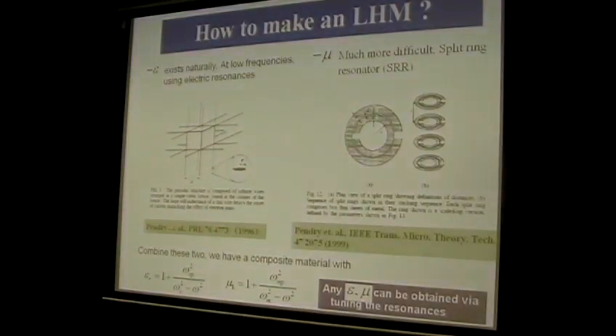The breakthrough came after Professor John Pendry proposed two structures which can have negative epsilon and negative mu at low frequencies. For this structure, he proposed that at low frequency we do not have plasma at all, however, we can make some kind of electron resonator system to still have an effective epsilon at low frequencies. And interestingly, he proposed that we can have split ring resonator structures. If this structure is on resonance, the current flows like this.